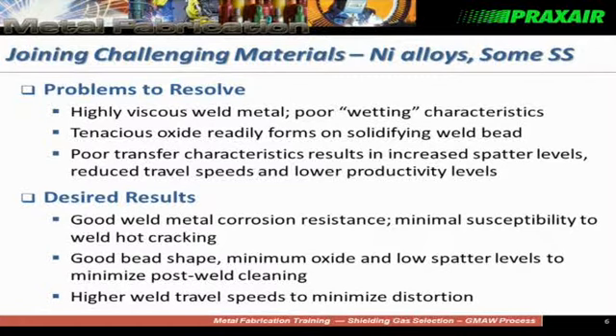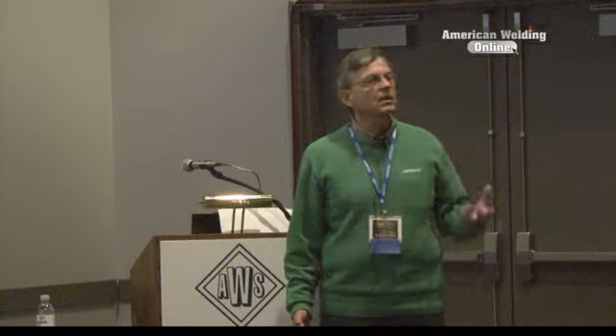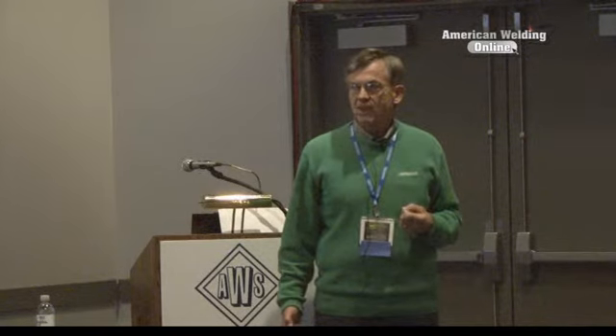Typically, in other welding operations, you might add something like oxygen or CO2 to a shielding gas to improve the fluidity of the weld pool. But with nickel, you get a very tenacious oxide on the surface that actually makes it harder to get the material to flow. So there's some real limitations as to what you can do. And it has very poor transfer characteristics. It tends to be pretty spattery, and again, weld bead shape is not real good.